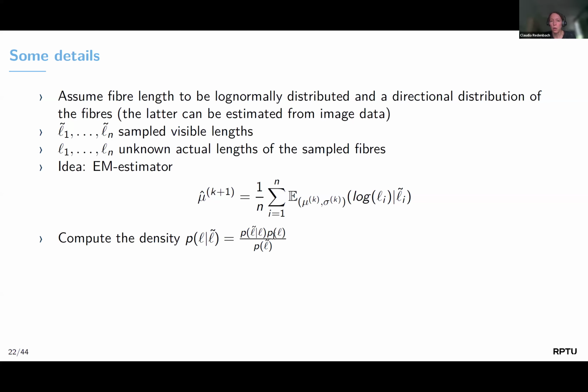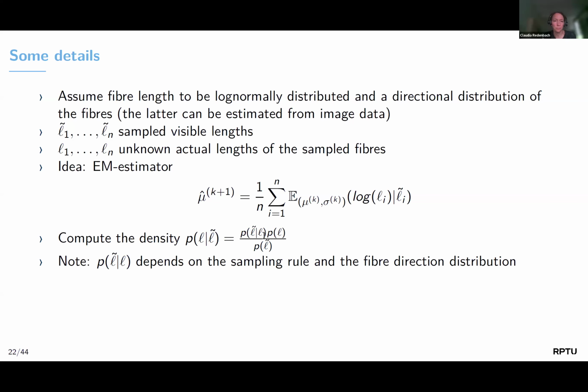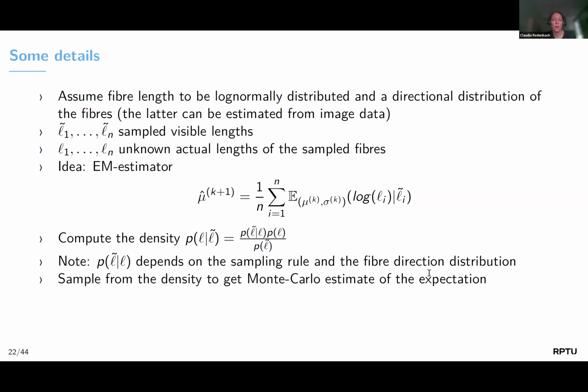So P of L is our log normal law, and the probability of L tilde given L can be computed by geometric considerations. So you could ask, if I have a certain fiber of a certain length, how likely is it that I see L tilde of that thing in my window? So that's doable computations to figure these densities out. However, different cases have to be considered, namely this density depends on the one hand on the sampling rule, so how do I decide which fiber to measure, and also the fiber direction distribution. And then we would sample from that density to get a Monte Carlo estimate of this expectation.